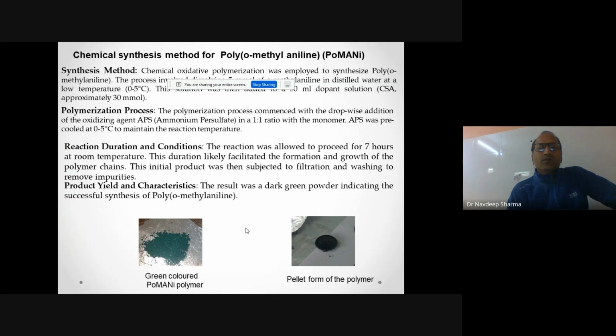After the proper mixing of the monomer and dopant, we started the polymerization process. For the polymerization process, we use ammonium persulfate as an oxidizing agent, and in a very gentle way, with dropwise addition of the ammonium persulfate as an oxidizing agent in the solution, the polymerization process starts.